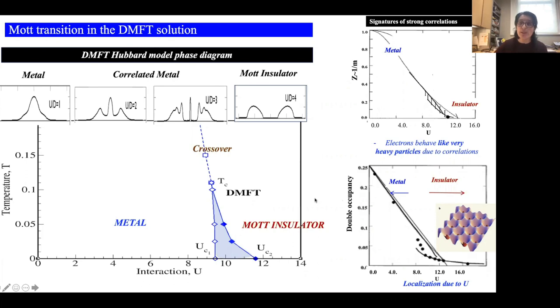So to demonstrate that this is really a correlation-driven metal-insulator transition, one can look at quantities like the quasi-particle peak or quasi-particle weight, which is inversely proportional to the effective mass, and plot it as a function of U and see that the quasi-particle weight is decreasing as you go from metal to insulator. And it is significantly suppressed as you go to the insulating regime, indicating that you are in the regime where correlation makes the electrons behave like very heavy quasi-particles.